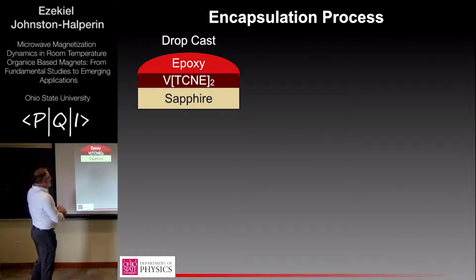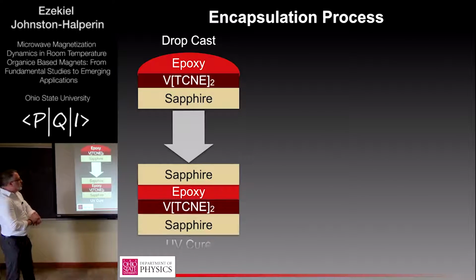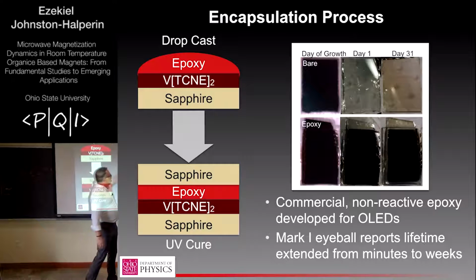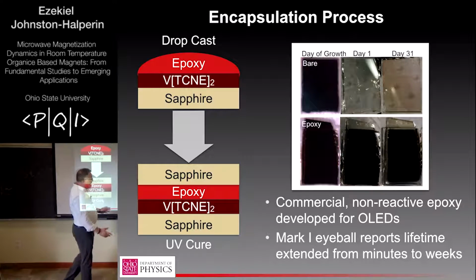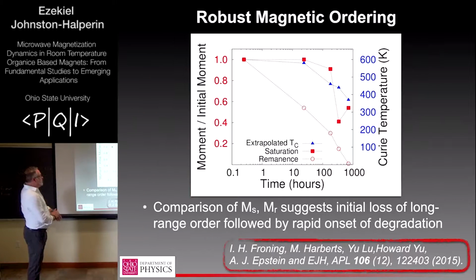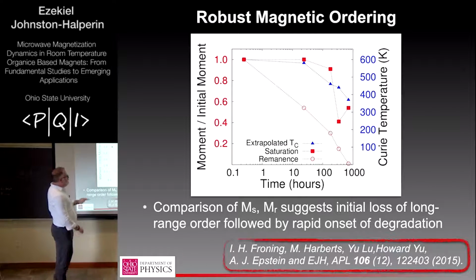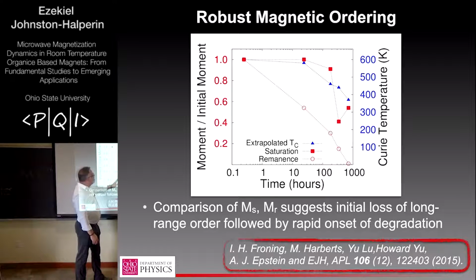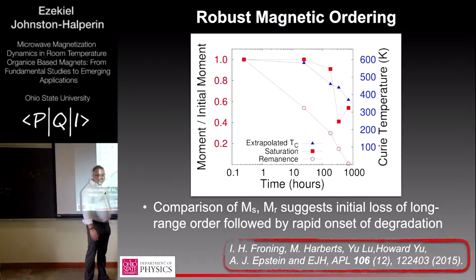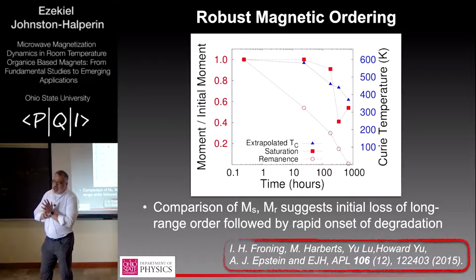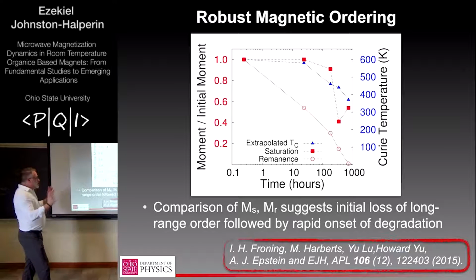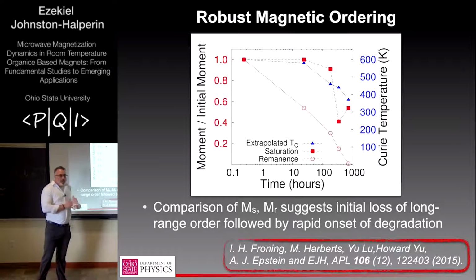So I'll just skip through this. This is basically what I said earlier: this is what happens if you leave an unprotected film out. If you protect it, it's good to the eye for a month. If you want to look at it a little more carefully, this is now log scale in hours. This point here is about 2 weeks as a calibration. The remanence dies faster than other properties, but this is just measuring the DC magnetization, and depending on what you care about, you can get a few weeks to a month out of it.